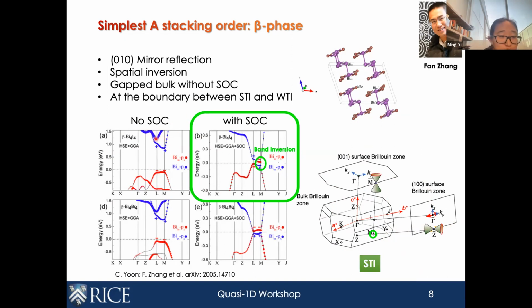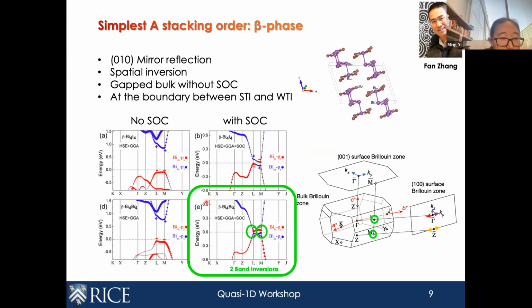Or you can slightly tune the size of these bulk gaps at different momentum points, which is demonstrated on the bottom row. Here we can realize two band inversions, and when you have two band inversions, as Fan's already nicely shown, they would annihilate when projected to the top surface, and they will give you two Dirac cones on the side surface, and therefore this will give us a weak TI. So you can see that the bismuth halides are actually at the boundary between where you can perhaps find a strong TI or a weak TI. And therefore, this is really an interesting system to experimentally identify what is the topological nature.